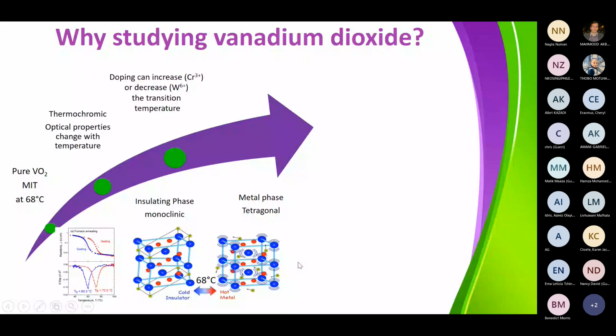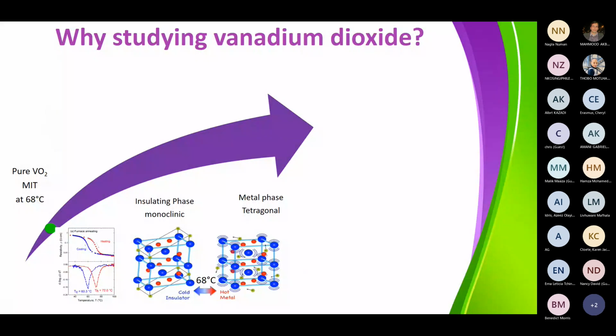All right. So why do we want to study vanadium dioxide? For those of you who know, this is not going to be very new, but for the ones who don't know about vanadium dioxide, this is a very interesting material because it has a metal insulator phase transition. So what does it mean? It goes from an insulating phase with a very high resistivity, like the one that you can see here, to a metallic phase, where the resistivity goes down with a very large variation, several orders of magnitude between the insulating and metallic phase.